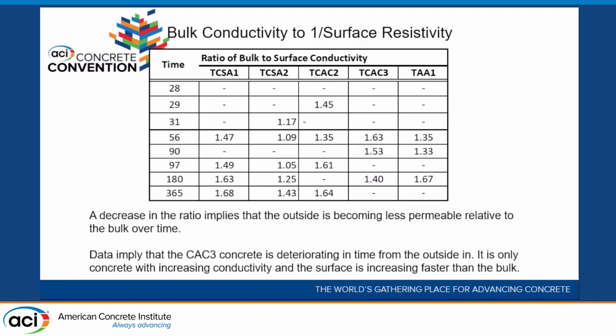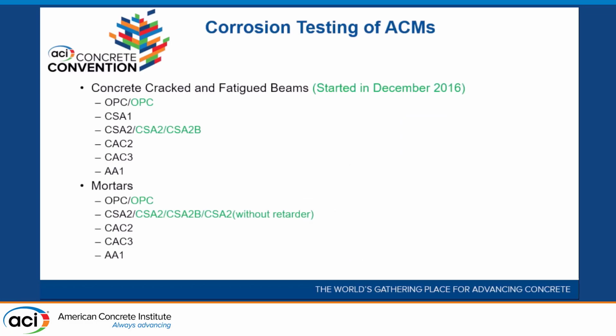We also looked at the ratio of the bulk resistivity to the surface resistivity, or the bulk conductivity to the surface conductivity. In general, a decrease in the ratio implies that the outside is becoming more permeable than the inside. And we see that for the CAC3 sample, which was the pure calcium aluminate, it was actually deteriorating on the outside where the water was coming in from in the fog room, with only fog room exposure for these.